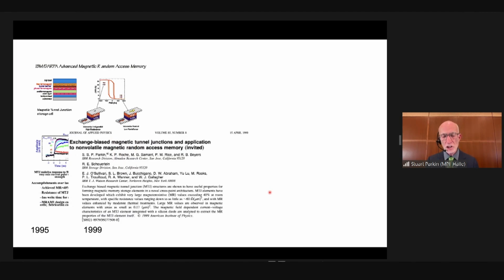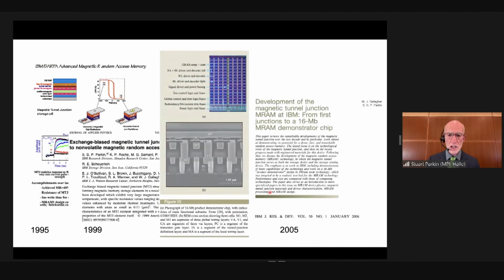However, within just 3 or 4 years, we could demonstrate, using conventional tunnel barriers, tunneling magnetoresistance values of more than 80% at room temperature. And later on, we further developed the tunneling magnetoresistance values, as I briefly mentioned, to more than several 100% at room temperature. This makes it possible to read the state of these tunnel junction elements extremely quickly.